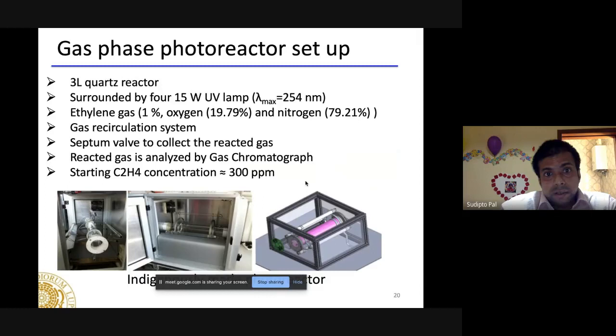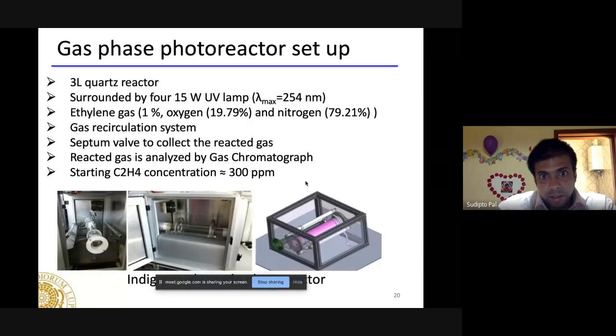In our laboratory setup, we test whether one photocatalyst is working or not. So in a photocatalytic chamber, we insert a specific amount of ethylene, and we put in one photocatalyst. It can be in the form of powder or in the form of any coated substrate. And with the gas chromatograph, we can see with time whether the concentration of ethylene is decreasing or not. So from this kind of experimentation, we can check whether one photocatalyst is working to decompose the ethylene.